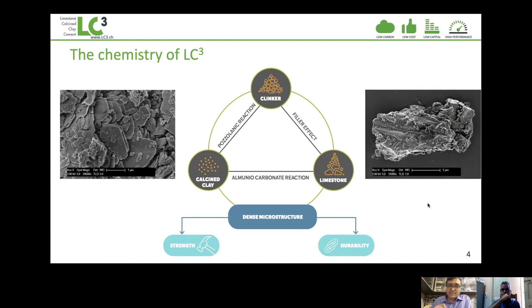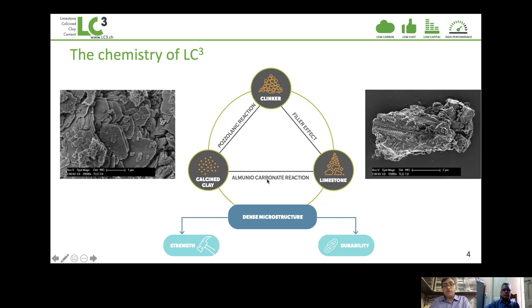That's where the magic of LC3 lies — the reactivity of the calcined clay, but also its reactivity with limestone. Without limestone, the clay would simply have a pozzolanic reaction with the clinker, where calcium hydroxide produced during hydration combines with the calcined clay to produce calcium aluminosilicate hydrate. However, the presence of limestone also leads to a reaction between the carbonates in the limestone and the alumina in the calcined clay. When these react together, they form carboaluminate phases, giving a denser microstructure with better strength and higher durability.